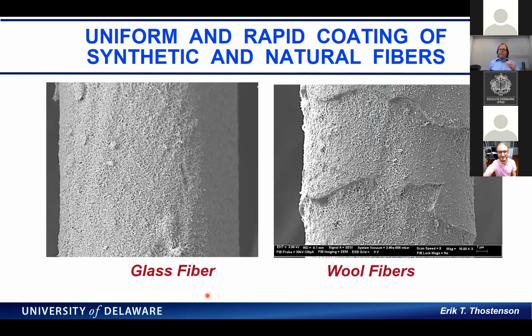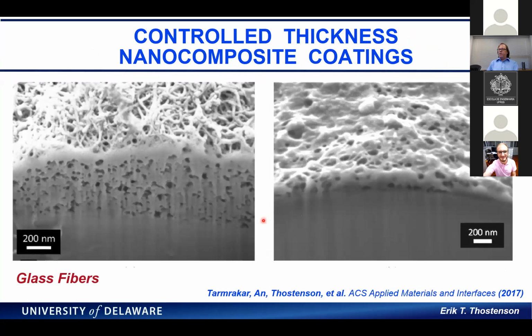And these are just some examples of where we've deposited on different fibers, and it doesn't just deposit on the fiber, but it completely surrounds each fiber in the bundle. So this is glass fiber, where you see a very uniform coating. We can also deposit on organic materials, such as wool, or things like aramid fibers, which would certainly disintegrate in a high temperature reactor. We also have a lot of control over the thickness. These are a couple of cross-sectional micrographs of where we've deposited at varying thicknesses.